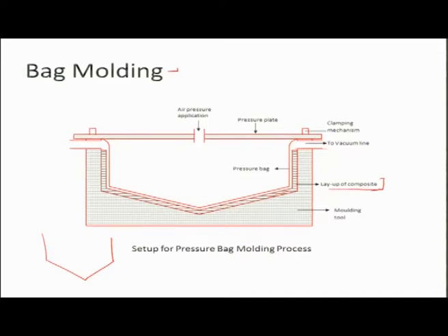have a pressure bag. So this is my pressure bag, okay, and what that means is the bag should have the same shape as the inside surface of the part. So if I want to change the part, I have to change this pressure bag, and from here I apply extra pressure. So I can put 20-30 atmospheres of pressure, and of course when this pressure is there, this presses uniformly.